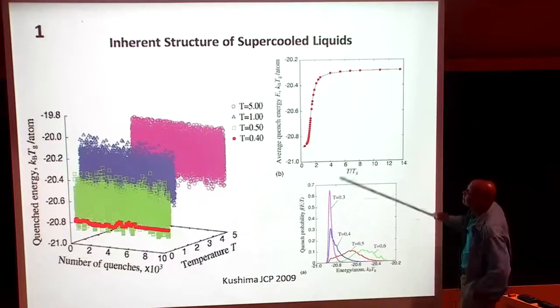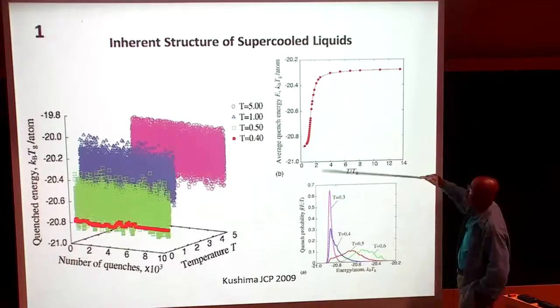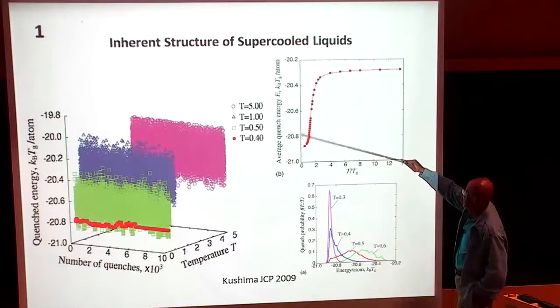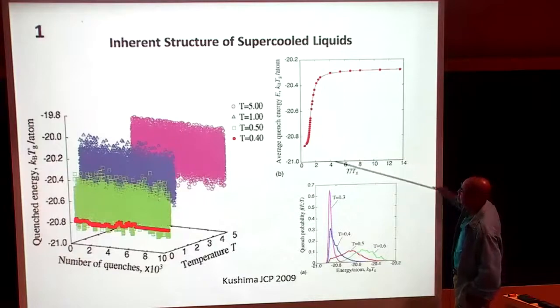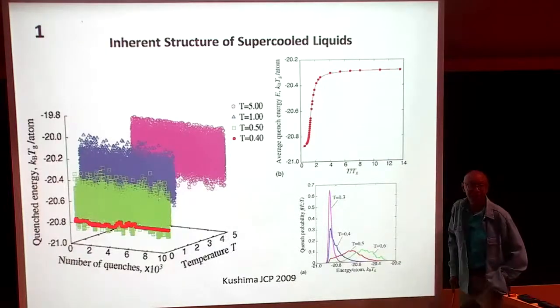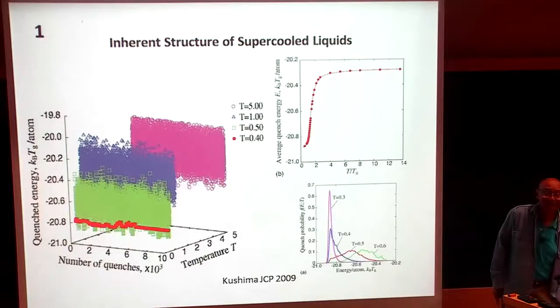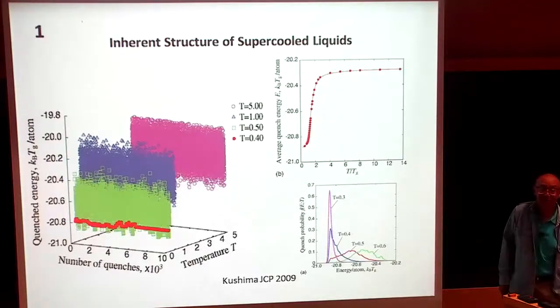All right, this is the standard. So this graph, Shastri knows very, very well. This is the inherent structure energy. A small comment: it's quenched from those temperatures. That's right, that's the start. The steepest descent quench is not at that temperature, but you start from that temperature and you get the inherent structure.